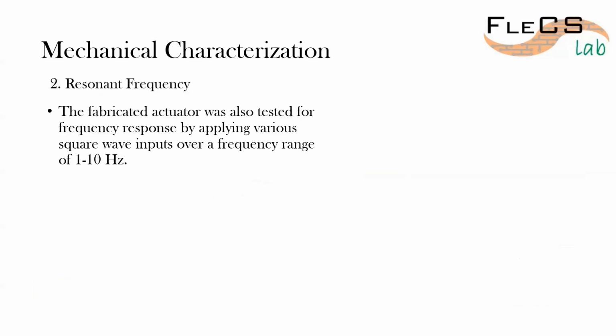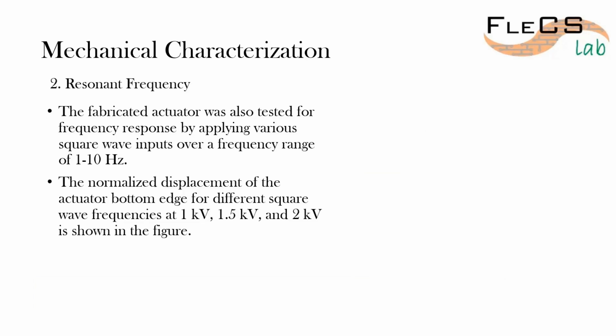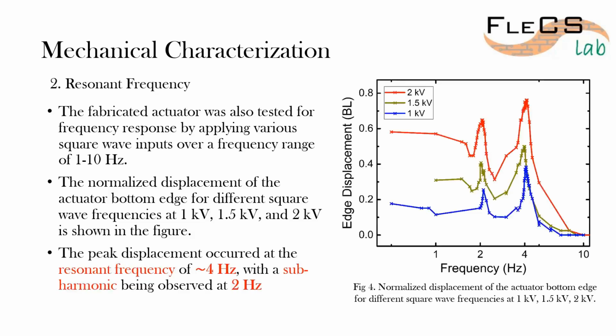So we looked at resonant frequencies between 1 and 10 hertz, and at different actuation voltages. And what we found is that it definitely resonated at a specific frequency, in this particular case 4 hertz. And one of the problems with DE is, again, we are happy that it's resonating at some point and giving us some displacement. But if you look at the roll-off for this curve, that is also pretty significant. So it absolutely stops displacing at 10 hertz.